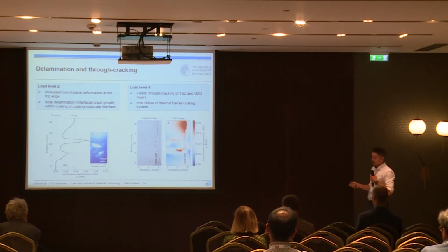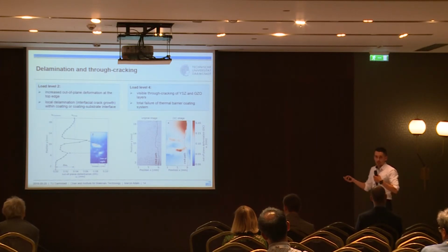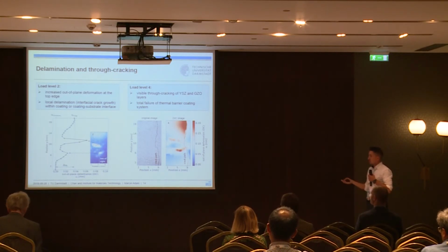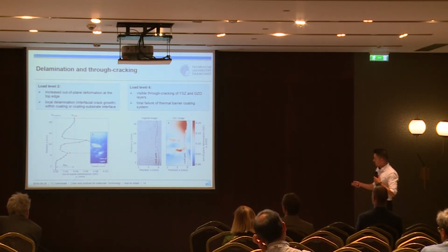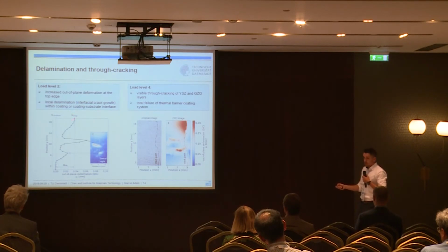Again, having a closer look at load level number 2, the state directly after TBC damage occurs, we can evaluate our out-of-plane deformation along one line. It's called the line of sight, which corresponds to the focus line of the cameras we used in the digital image correlation. And note these red spots fit to the peaks in the out-of-plane deformation graph. But also note the gap between the top edge out-of-plane deformation and the bottom edge out-of-plane deformation. This gap is a local delamination or interfacial crack growth within our coating, starting from the top edge.